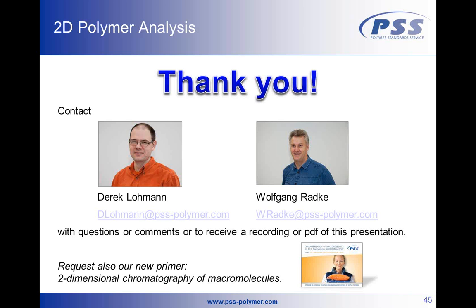There is one method which is called molecular topology fractionation, which was invented by Dow and furthermore investigated in the group of Peter Schoenmakers, where you do separations in very, very narrow channels. A branched polymer needs to be more stretched than a linear one, and that means if you press them through a narrow channel, you get different retention times.